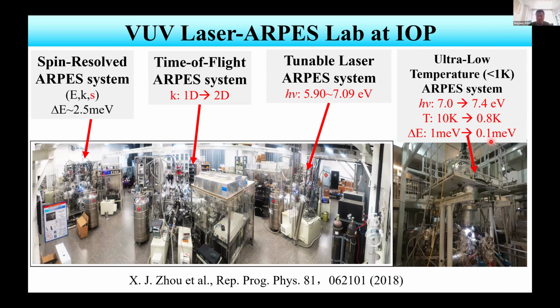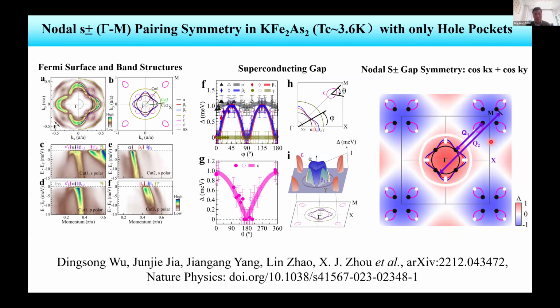Because of this development, recently we have measured the superconducting gap symmetry in the potassium iron arsenide system. This system is very interesting because it has only hole pockets, not only near the gamma point, but also near the M point. So it's interesting to see what pairing symmetry this system has. But this system has a very low Tc, only about 3.6 Kelvin, and the maximum gap size is only 1 meV. That's why it's very difficult to do the measurements.